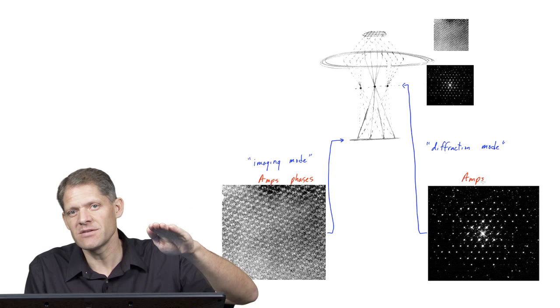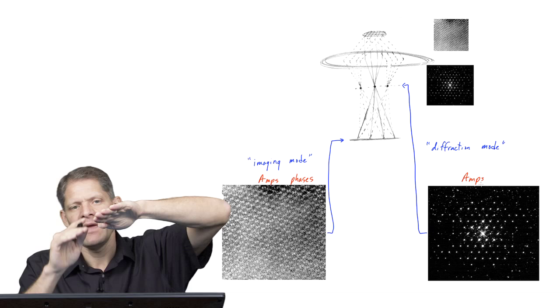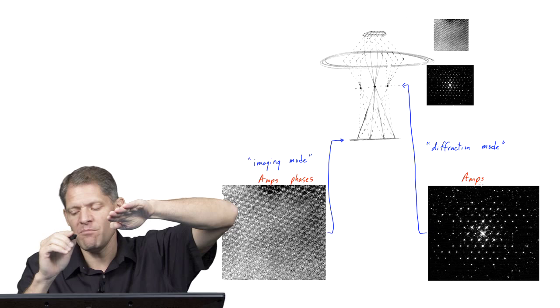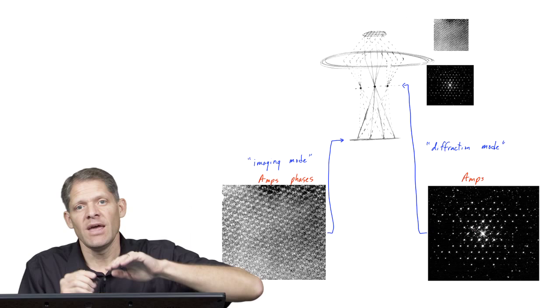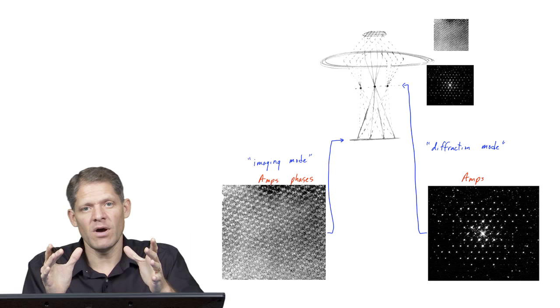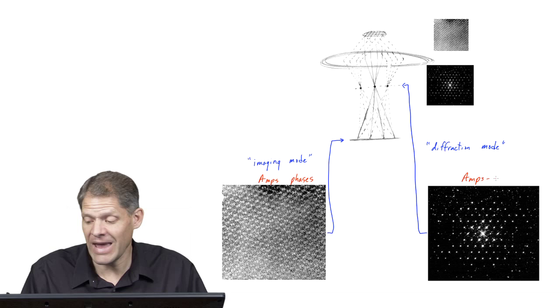However, because these amplitudes are shift invariant, meaning that if the crystal is drifting slightly in the microscope as it's imaged, that slight drift doesn't impact the amplitudes of the spots in the diffraction pattern. Even though the crystal is drifting just a little bit, you can still get clean measurements of the amplitudes. So the best way to get good measurements of the amplitudes is through diffraction mode.